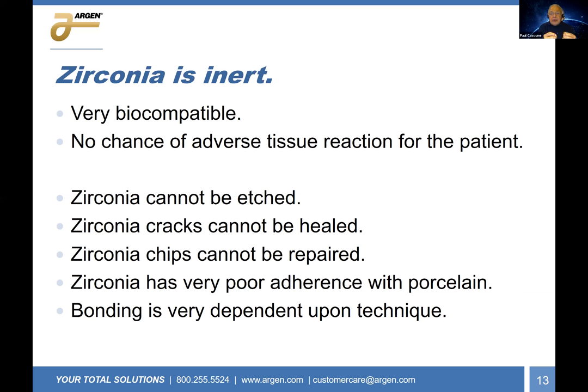But because it's so inert, we have problems with it with regard to what we're used to. It can't be etched like dental porcelain could be etched. Zirconia cracks can't be healed. If you had a little crack in the porcelain, and maybe when you made an adjustment, you could just put it back in the furnace, and the glass would flow and it would reheal. You can't do that with zirconia. There's no glass. The chips can't be repaired. Once it cracks, it's gone.